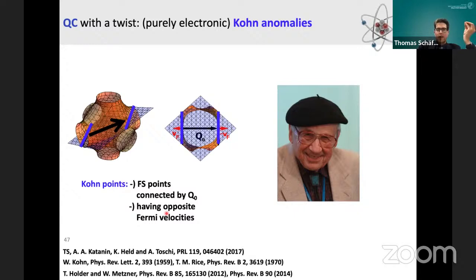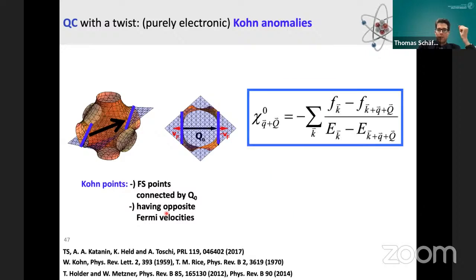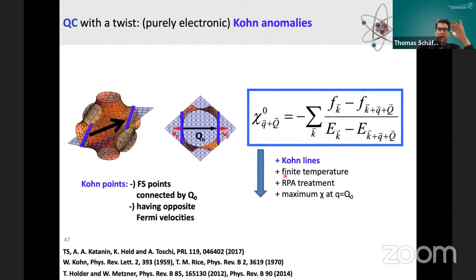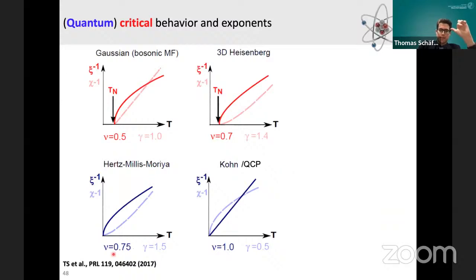So what influence does this have on our critical properties? The details of the calculation I want to spare you. We did a mean field calculation, where we introduced also the Kohn lines at finite temperature. The outcome was that the critical exponents of the QCP actually changed, quite dramatically, from nu 0.75 to nu 1 and gamma 1.5 to 0.5. This is quite unexpected because we are at quite strong coupling, so we have a high U. You wouldn't expect that the band structure is really much important for the critical exponent at strong coupling.